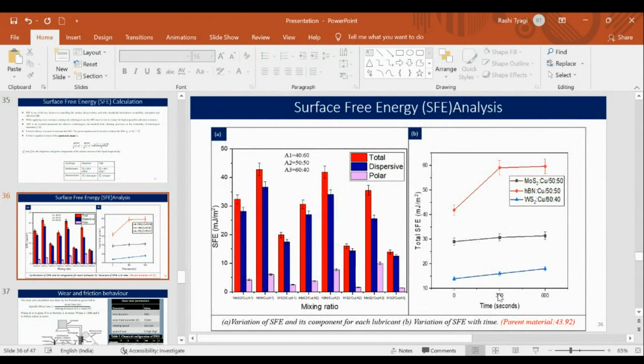These are the values that we have plotted in the graph, in which you can see that among the different values of surface free energy, the minimum surface free energy is observed for the WS2 plus copper coating, which you can see from the figure.